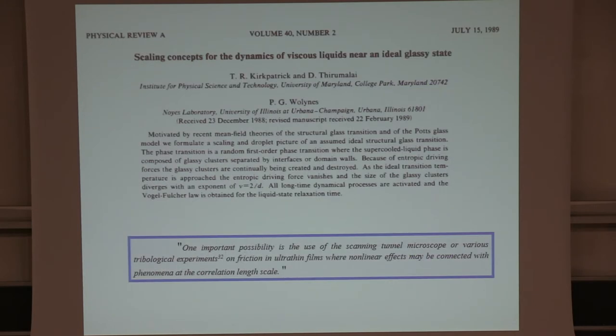Now, of course, this length being fixed is something to go after. And it's very hard, though. This is a size range which is not easy to measure. I'd asked one of my colleagues at Illinois, Jerry Jonas, to try to do experiments where you would put liquids inside of little vesicles, and he started to show that there were effects, but it really was very hard to measure the glass transition in these confined liquids.